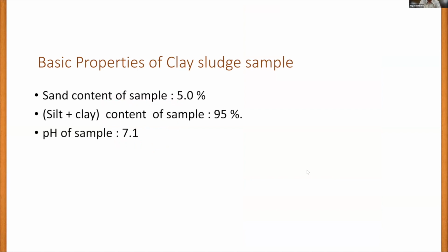need not mean sand actually. It is more or less whatever material we got above 75 microns. Normally it is called sand content, but in this particular case, not much sand we could find. But silt and clay together was about 95%. We have not yet determined the silt and clay percentage. We need to do another analysis for that, but that's not something very important at present. The pH of the soil sample was 7.1. So these are some basic parameters.